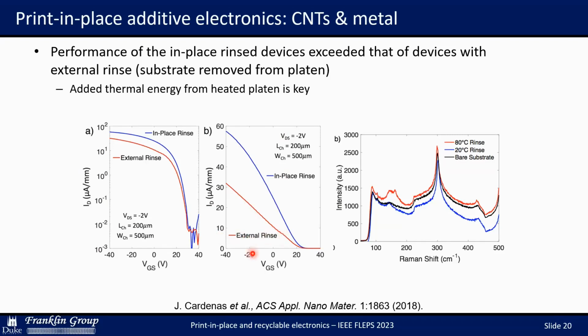more traditionally processed one where you remove the substrate, rinse off the residual organics outside of the printer, it performed worse than the one that was left in place of the printer. There is a reason for that. It came down to the fact that while the substrate remained on the printer, it remained heated on the platen. So when we performed a rinse to remove the organic residue with the substrate in place, it actually was aided by the thermal energy of the heated platen to drive off a more effective rinse.